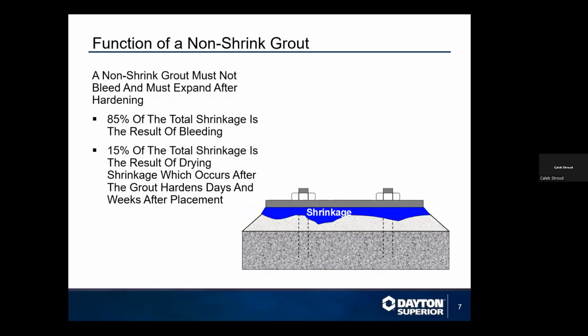A non-shrink grout must not bleed and must expand after hardening. 85% of the total shrinkage is the result of bleeding, and 15% of the total shrinkage is a result of drying shrinkage, which occurs basically after the grout has been cured.